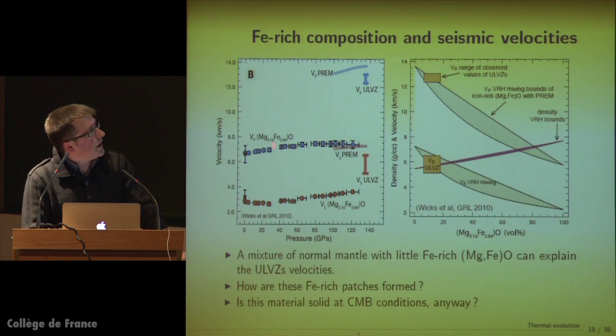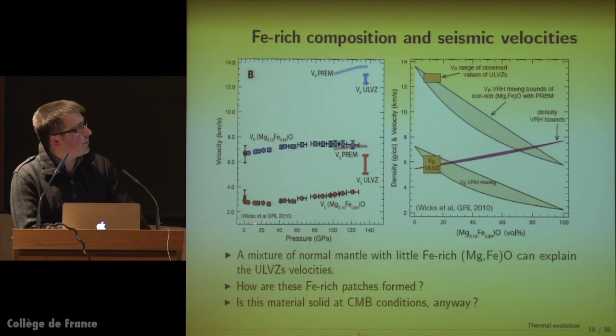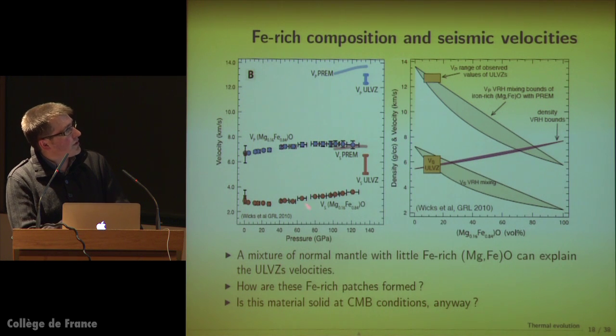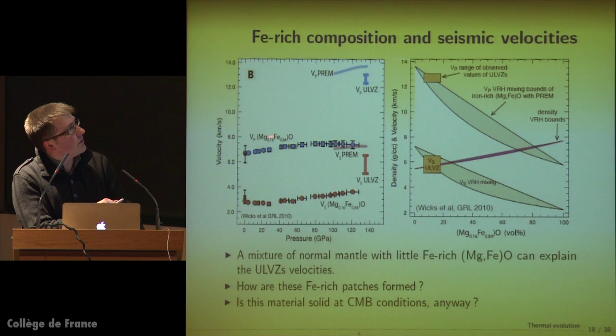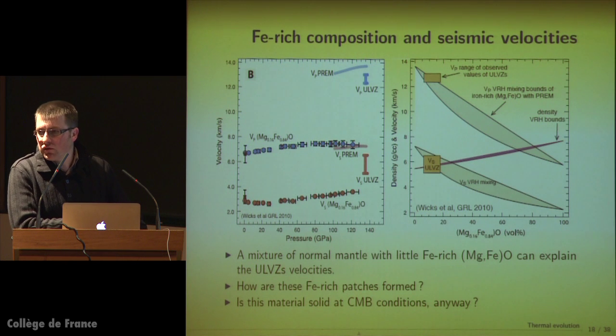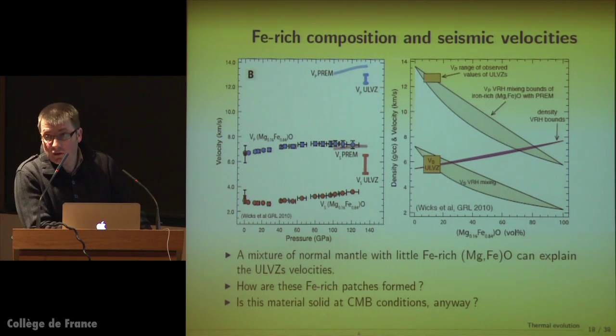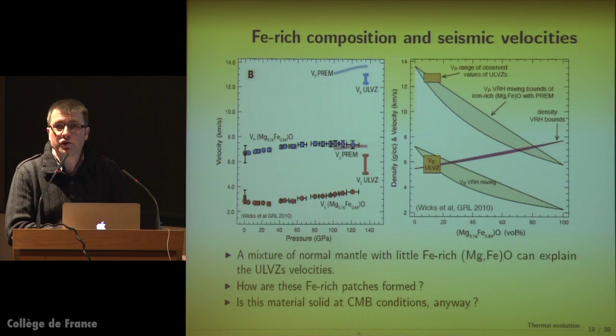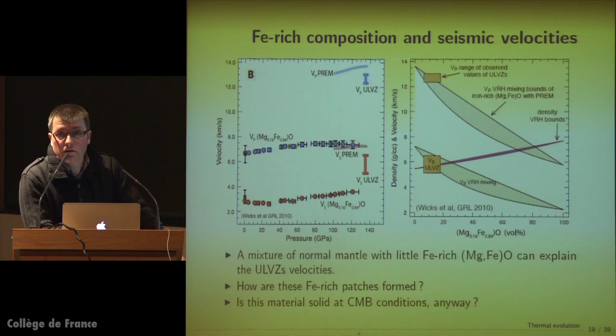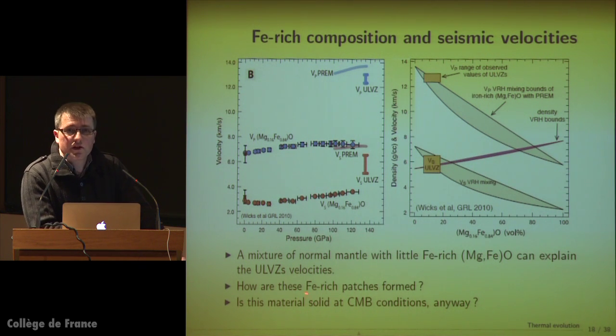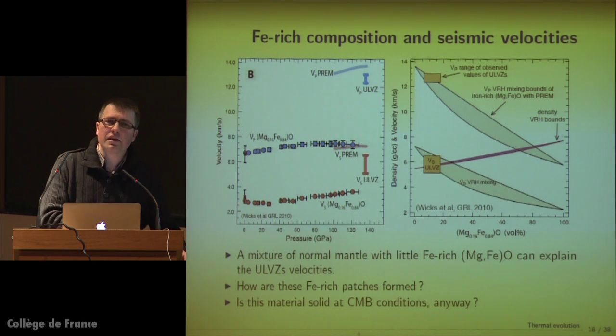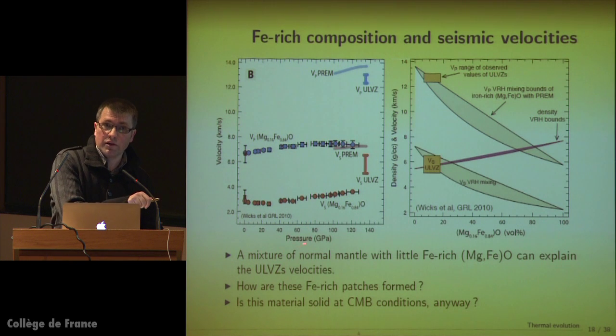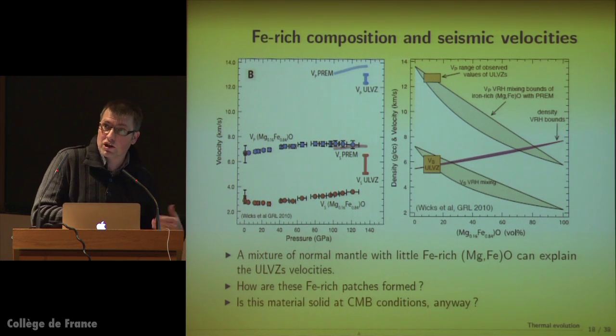The interpretation in terms of solid is essentially one of these recent papers. This is velocity measurements as a function of pressure for a composition that is very iron rich, okay? And so by mixing about 10% of this very iron rich composition with normal mantle, you can match the VP and VS reduction in ULVZs in the solid state. That's the main argument in this paper. The problem is, of course, how do you make such highly enriched iron patches in the first place? Probably the best way to do it is actually by fractional crystallization.